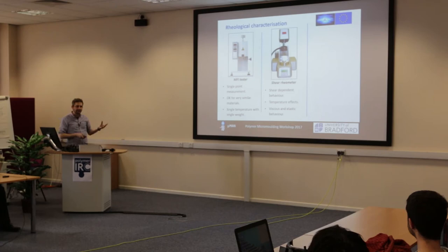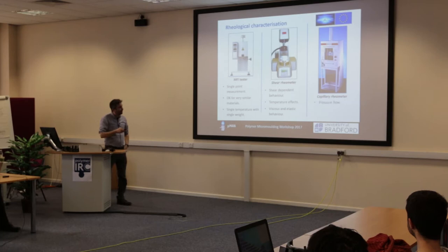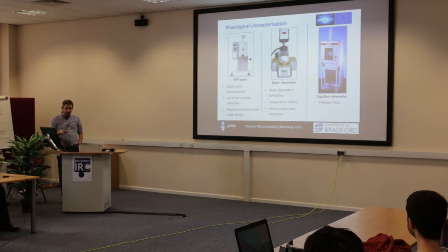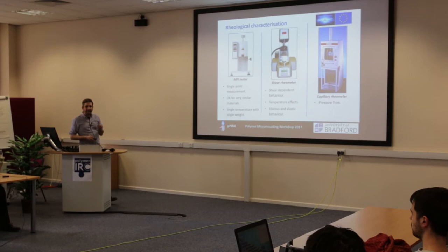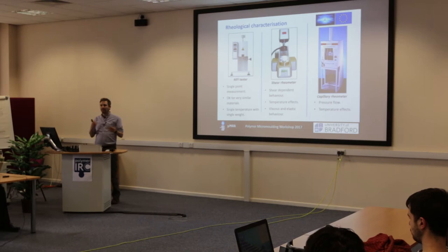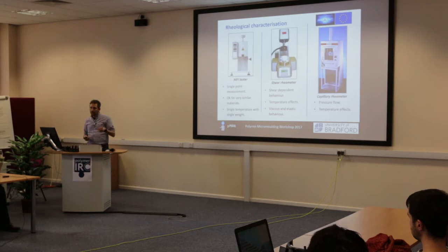Now the other technique that you'll be introduced to this afternoon as well is a capillary rheometer, which is a pressure flow. The pressure flow is pretty interesting on the grounds that that's fundamentally how you make a product, by pressurizing your material as you flow it through a die, okay? So it's a good replica of a true process. However, it's incapable of measuring anything about the molecule itself, really. It just tries to push, and then it measures how difficult it is to push a material. Okay, so you lose complexity, but you get closer to the process.